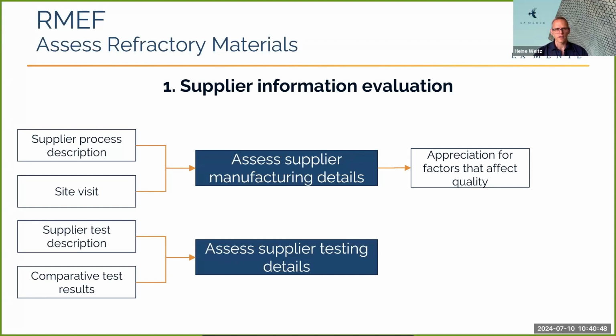Okay, then we also need to look at the testing details. So when you receive refractory materials, you get a data sheet with test results. The question is always how reliable are those test results? So again, one can look at the test descriptions, if that's available, look at the quality standards that are being used, and also how those test results compare to comparative tests that were done, either by the refractory supplier or by doing it yourself. And again, that gives you confidence or identifies shortcomings in the test results. So to a large extent, this is a qualitative assessment. It's a fairly low-cost assessment, with no detailed calculations that you need to perform, but it is a way of quickly identifying if a supplier will be able to provide you with refractory material that is of high quality.